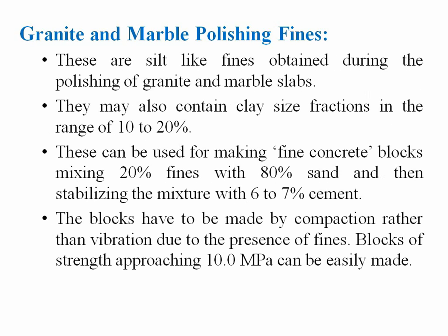And next, granite and marble polishing fines. These are silt-like fines obtained during the polishing of granite and marble slabs. They also contain clay size fractions in the range of 10 to 20%. These can be used for making fine concrete blocks, mixing 20% fines with 80% sand.